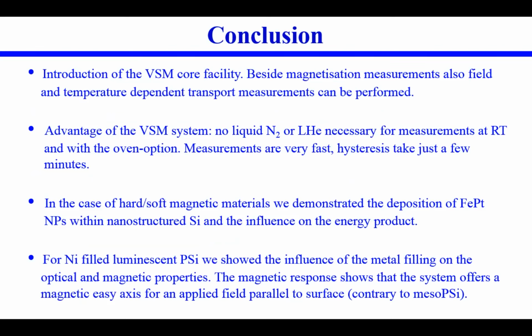The measurements are very fast, so hysteresis takes just a few minutes, which allows the performance of such measurements. And this is in contrast to a SQUID magnetometer. A SQUID magnetometer always needs liquid helium, even for measurements at room temperature, and it's very slow. So hysteresis would take many hours, for example, on average 8 hours, and here you need a few minutes.